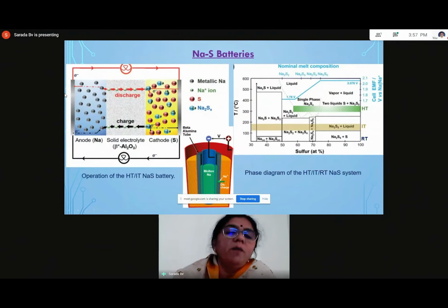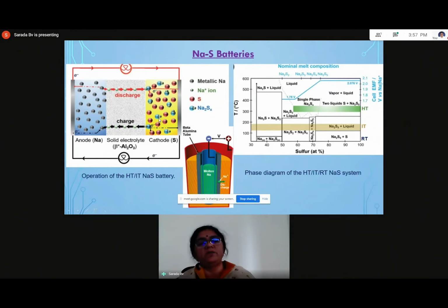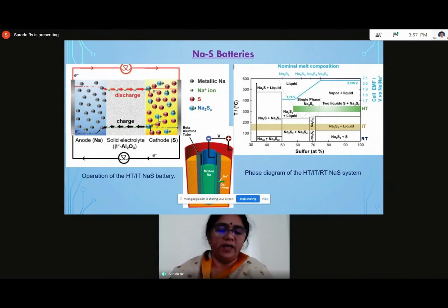So the operation of sodium sulfur battery: the high temperature sodium sulfur batteries use anode and cathode in the form of molten liquid, and a solid electrolyte of beta alumina is used between the two, and the sodium ions diffuse back and forth during the discharge and charge process. Again, another problem with these high temperature batteries is that they produce plenty of polysulfides, the same as in the case of lithium sulfur batteries.